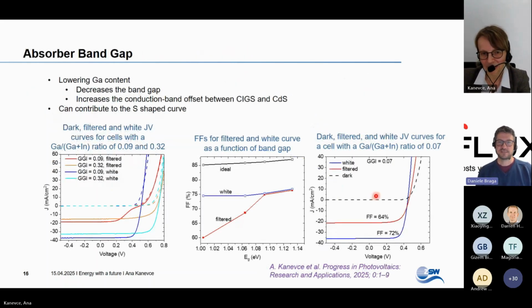And the other one is just at the beginning, you mentioned that CIGS can be used as bottom solar cells, but also as top solar cells. If we inverted the structure and we fabricate tandem with perovskites, do you see an increase of the stability of the tandem? The perovskite is protected. Do you see other problems? Can you comment on that? You mean invert the structure having CIGS as a bottom cell and perovskite on the top?